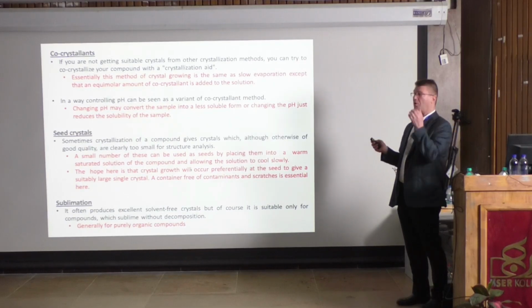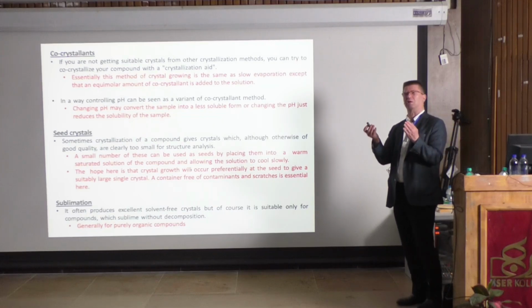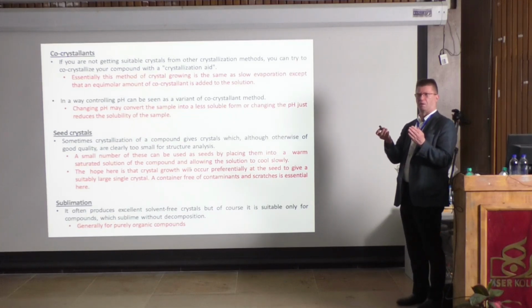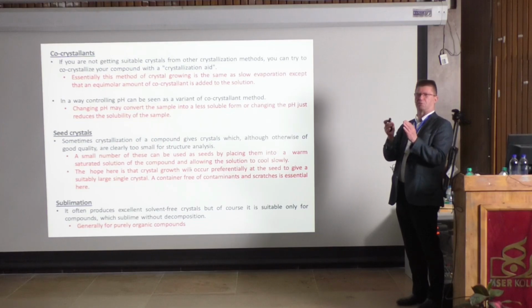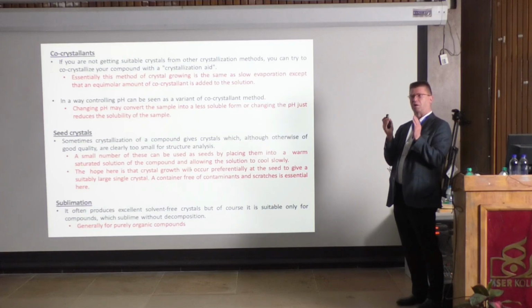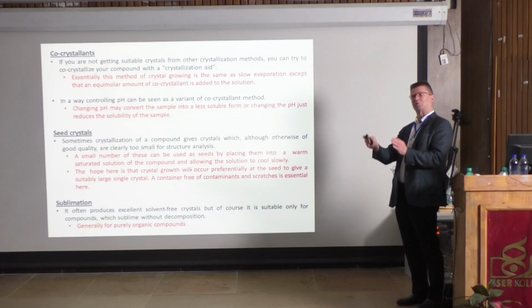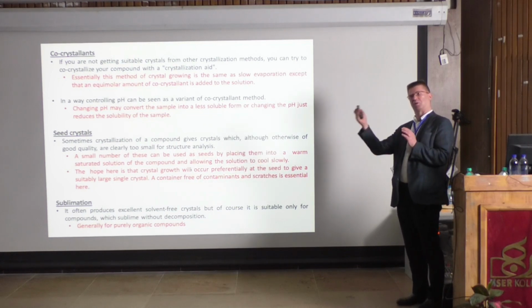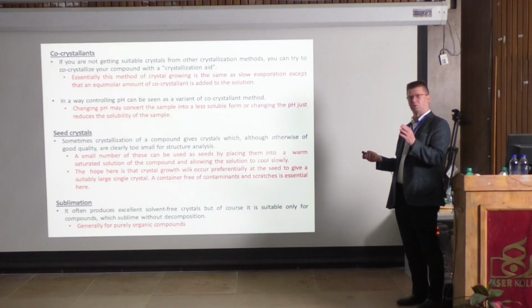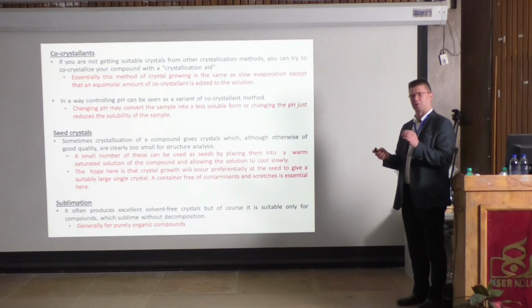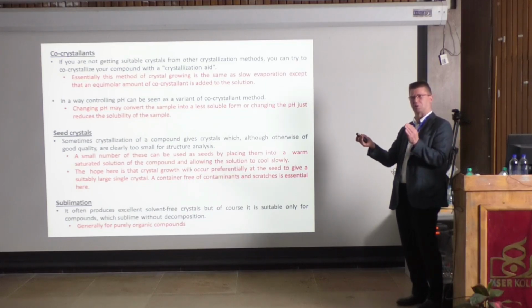Then it's okay, let's try this co-crystallizing and add another component. We thought, maybe there is hydrogen bonding or pi-pi interaction or any kind of additional interaction between these components. We did it, and it turned out to be yes. We were lucky. We got 1 to 1, so there was both A and B in the crystal structure. At the same time, we got the structure of our target molecule and the component B.